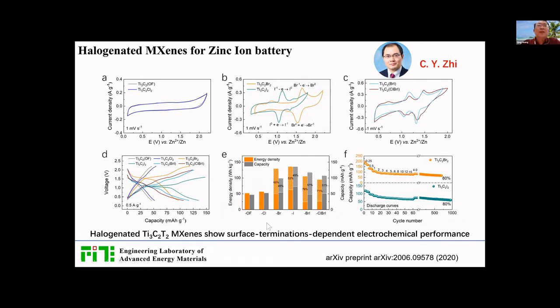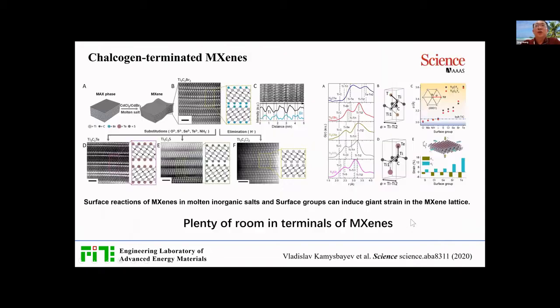So that means there is more work to do on the surface termination of the MXene to change their properties. Here is some new work published in Science. You see that we can further make some replacement of the anion on these bromine MXenes to make chalcogen-terminated MXenes. And this work even shows that some MXenes show superconductivity. I think it largely expands the application of these MXene materials.